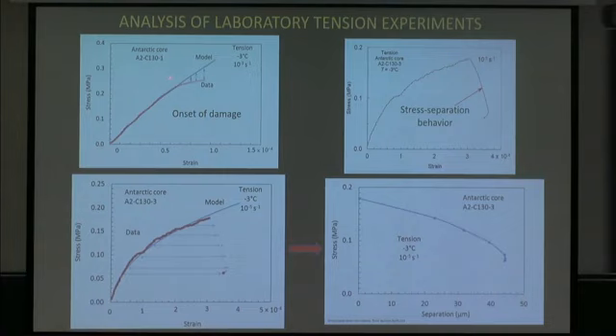You can basically, the blue would be, all right, this is loading at that temperature and that strain rate. You see a real nice agreement. And then you can tell things like, oh, at this point, that's when I started inducing damage. So you can start getting very rational about analyzing these results in terms of damage propagation.